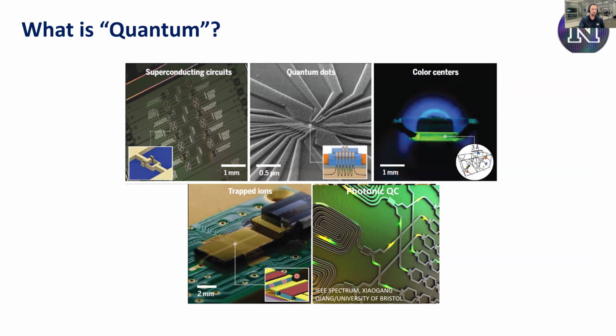In the color center space, which I'll talk about towards the end of the talk, we see the zero phonon line for silicon carbide color centers wander around. And if you look at the y-axis here, these are on human timescales, over the course of an hour. Superconducting qubits, people will report coherence times, but as everyone in the community knows, those coherence times fluctuate wildly. Now, this is for a device that's at 10 millikelvin, and still the coherence time, the amount of time that it can maintain its state, fluctuates wildly because there's some kind of long-lived interaction, something out there that our qubit can interact with.